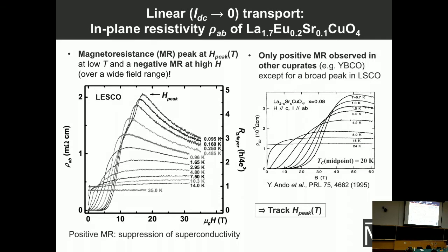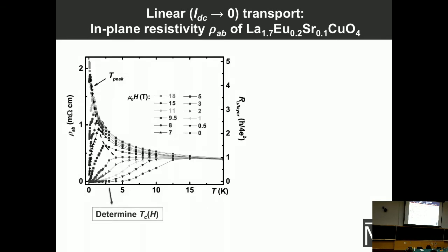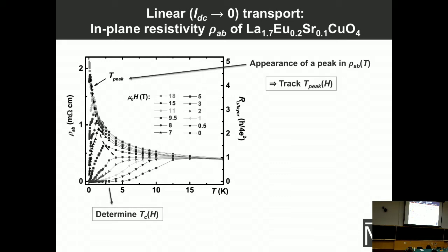We can use the same data to extract the temperature dependence of the resistivity for different fields. Here is what it looks like. You see that as we increase the field, TC is suppressed, so you can map out the dependence of TC on the field. We also see that at some point this temperature dependence starts to develop a peak, which also depends on the magnetic field. So this is another characteristic feature that we can track.